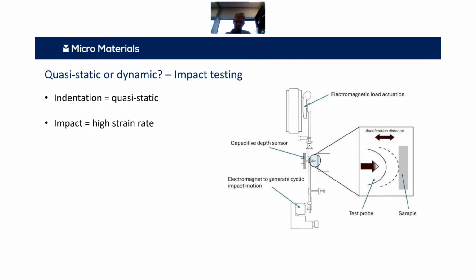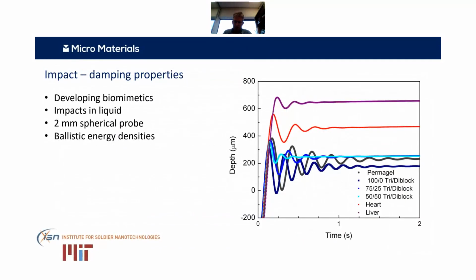So one of the first situations where this type of thing was done on biological samples was at MIT, when they were looking at trying to simulate the damping response of different polymeric systems and match that damping response to various tissues as part of developing armor for the US military, essentially. So in this case, these are very soft samples being impacted through liquid, and rather than these very small diamond probes, now we're getting a small, few millimeter spherical probe, and you can achieve some quite high densities with this testing.